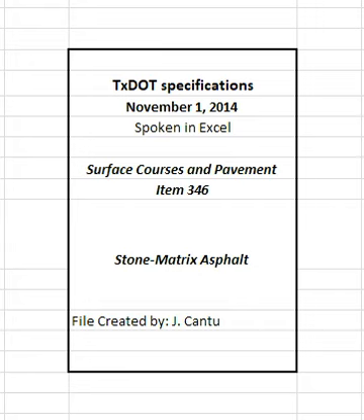Obtain cores in areas placed under exempt production, as directed, at locations determined by the engineer. The engineer may test these cores and suspend operations or require removal and replacement if the in-place air voids are less than 2.7% or more than 8%. Areas defined in section 346.4.9.3.1.4, miscellaneous areas, are not subject to in-place air void determination.